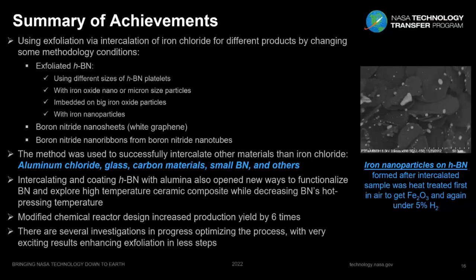Intercalating and coating hexagonal boron nitride with alumina also opens new ways to functionalize boron nitride and explore high temperature ceramic composites while decreasing the boron nitride hot pressing temperature. We modified the chemical reactor design to increase the production yield by 6 times. And there are several investigations in progress optimizing the process with very exciting results, enhancing exfoliation in fewer steps. And that's what we want, to also use fewer chemicals. Next slide.